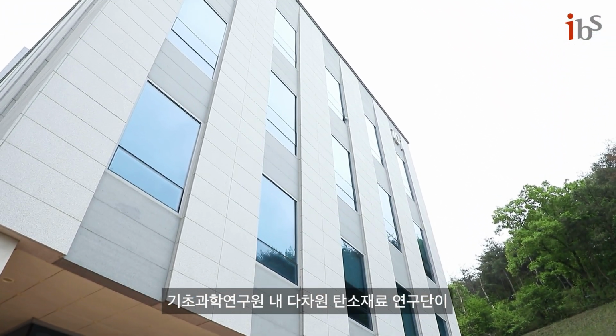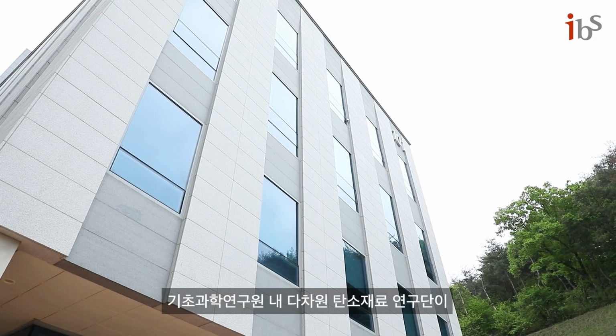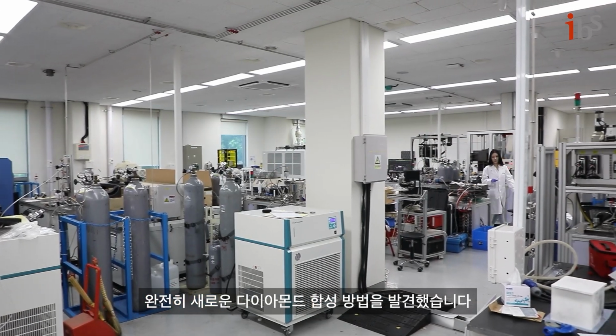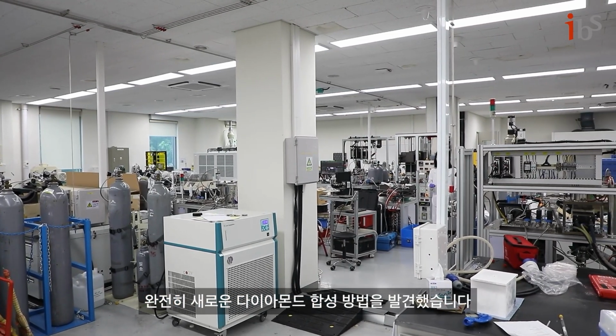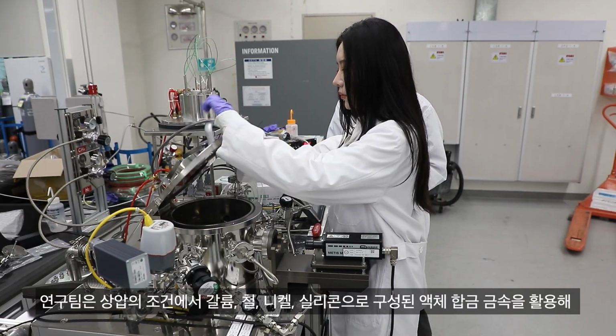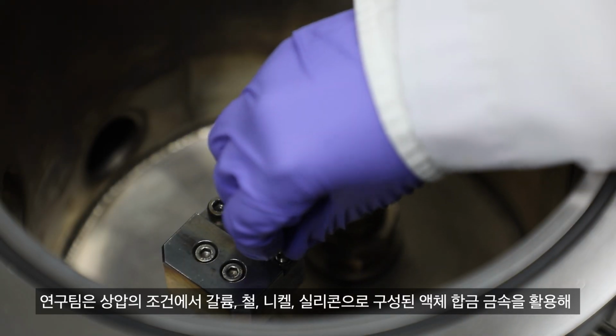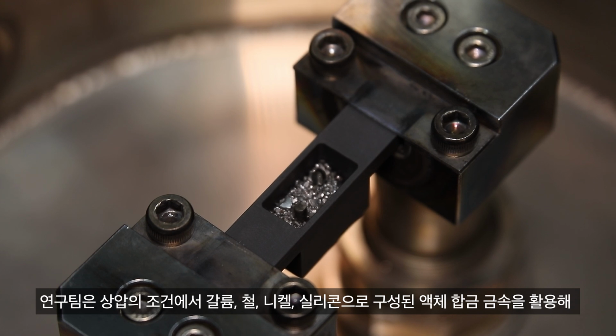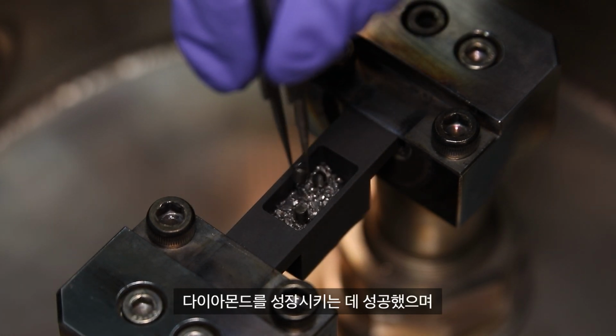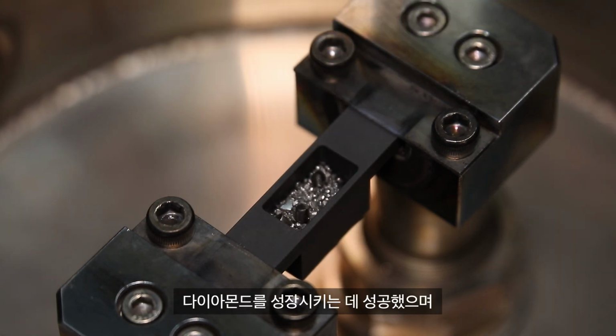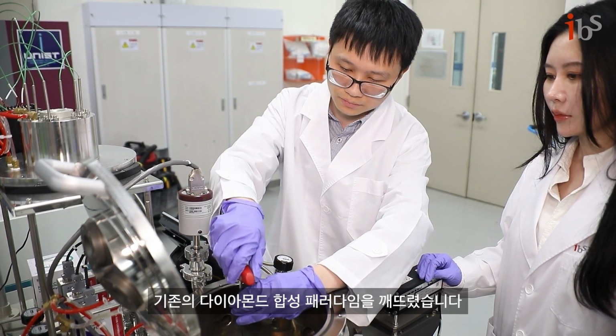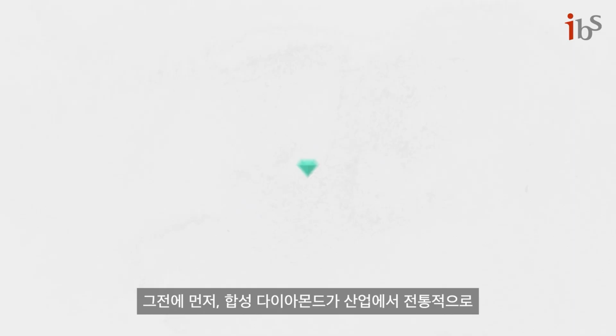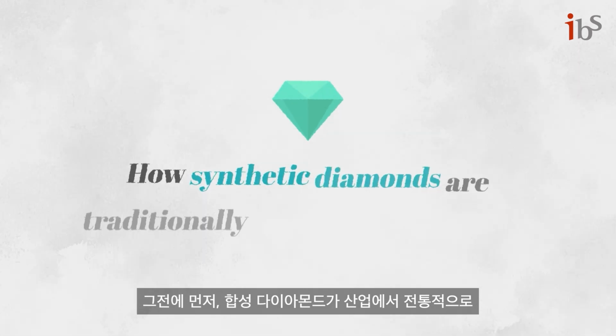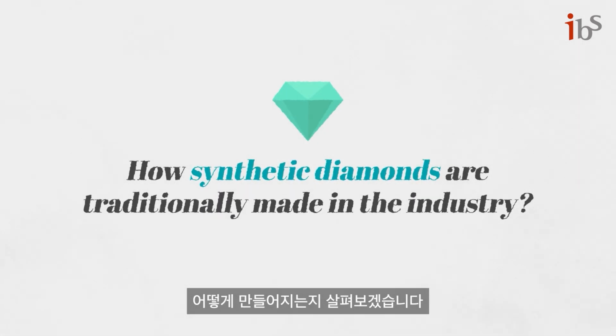Center for Multidimensional Carbon Materials within the Institute for Basic Science has discovered a completely new way to synthesize diamonds. The team was able to grow diamonds using a liquid metal alloy composed of gallium, iron, nickel, and silicon under ambient pressure condition, breaking the existing paradigm of diamond synthesis. But first, let's take a look at how synthetic diamonds are traditionally made in the industry.